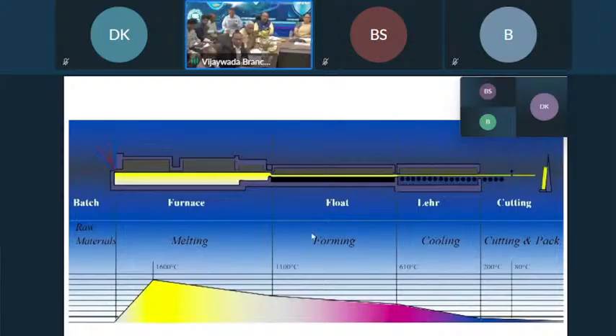In this place where forming takes place, you have to observe the temperature of your glass will be 1100 degrees centigrade at the time of pouring. Then after the forming takes place, at the end of the forming we'll get the glass temperature of 610 degrees centigrade. So here the glass will become hard to soften, or there may be breakage of the glass. If you take the glass suddenly open to the air, the glass may break. So that's why you go for the annealing process in a stepwise manner, 610 to 200 degrees centigrade.